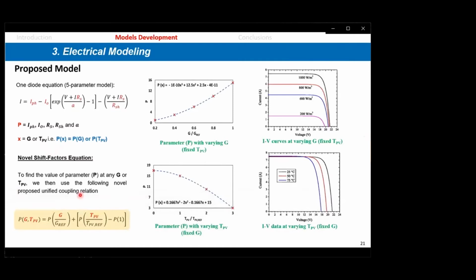So if we take one of these 5 parameters, call it P, and the variables are either irradiance or cell temperature. Then we took the IV curves from the data sheet for different irradiances and for different temperatures, and we tried to fit the results, the IV curves, and see how each of these 5 properties evolves, either with irradiance or with temperature. And from this, we were able to come up with a unified relationship that gives any of these 5 parameters as a function of both irradiance and temperature in this form here.